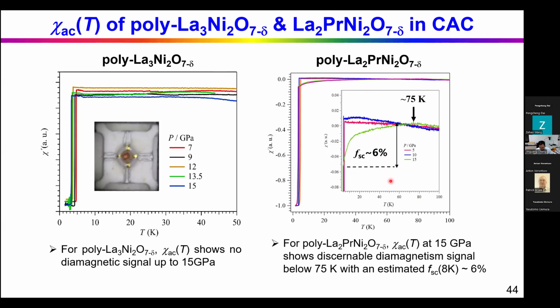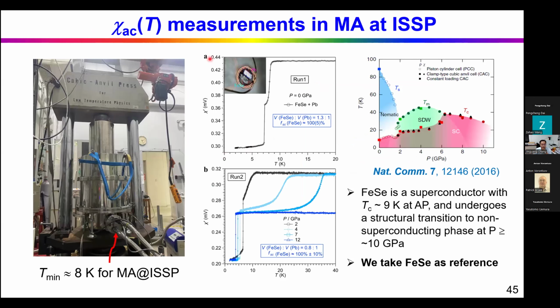So how about at higher pressures? Then we measured with the multi-anvil cell in Japan, at the Institute for Solid State Physics, University of Tokyo. This is the setup. They use a closed cycle refrigerator to cool down the large cell, but at that moment the lowest temperature is about 8 Kelvin. So we cannot use lead as a reference because the transition of lead is below 7 Kelvin. Then we chose iron selenium as a reference because in our previous studies we are very familiar with its transition. It's a superconductor at ambient pressure with TC around 9 Kelvin. Under high pressure, the TC goes up, and the highest TC is around 38 Kelvin at 7 GPa.